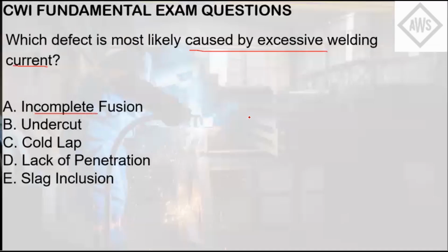Incomplete fusion is normally the result of low heat input, so that's not excessive welding current. Cold lap is similar, usually insufficient heat. Lack of penetration, same, usually insufficient heat or low current. Slag inclusion is not necessarily related to heat input, but more to the technique or cleaning methodology of the welder. So the answer here is letter B, undercut. That results from excessive current, thus resulting in undercut, letter B.